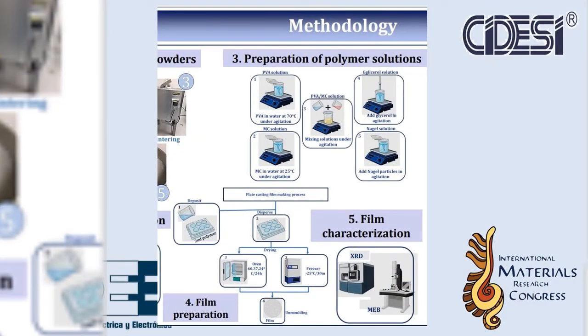For the preparation of the polymer membranes, solutions of PVA-MC and PVA-MC with and without glycerol and Nagelschmidtite particles were fabricated. Subsequently, the membranes were manufactured by the plate casting method, and the drying and shaping was studied by two methods: convection drying and freeze-thaw cycle drying, where a physical cross-linking is induced to stabilize the matrix and obtain the polymer membrane. The fabricated membranes were characterized by XRD and SEM to determine the dispersion and presence of the ceramic particles in the polymeric matrix.